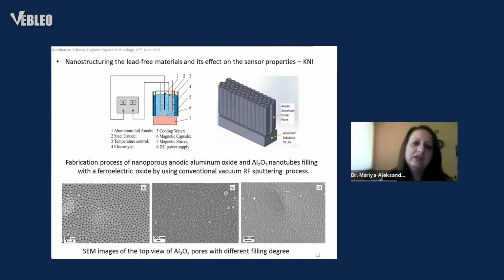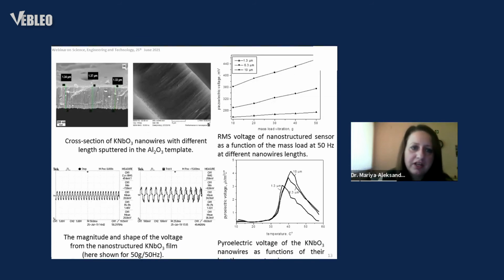And the filling of the nanotubes is again by conventional microfabrication sputtering process. At the bottom of the slide, you see scanning electron microscope images of the top of the pores. It's captured at different stages of filling. Here it is completely empty, here it is partially filled with potassium niobate, and on the right side completely filled with the potassium niobate. So here you can see the cross section of these nanowires.